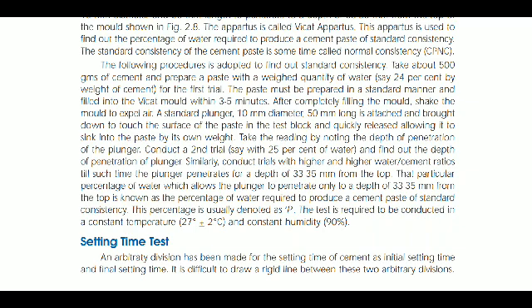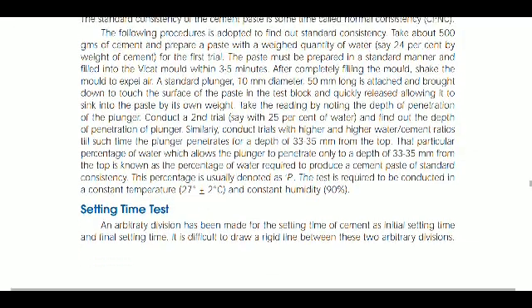Similarly, conduct trials with higher and higher water-cement ratio until the plunger penetrates to a depth of 33 to 35 mm from the top. The particular percentage of water which allows the plunger to penetrate only to a depth of 33 to 35 mm from the top is known as the percentage of water required to produce a cement paste of standard consistency. This percentage is usually denoted as P. The test is required to be conducted at a constant temperature of 27 degrees plus or minus 2 and constant humidity of 90%.